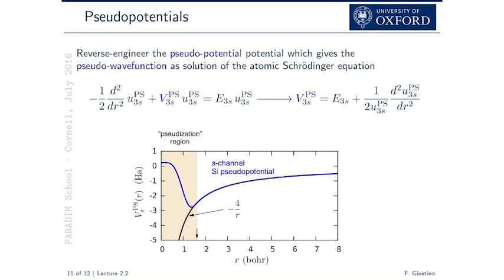So this operation actually is absolutely critical because, what you can try as an exercise if you want today, try to do any of the examples you did, okay, crank up, so you use maybe a cutoff of 25 Rydbergs, try to do the same calculation and put 500 Rydbergs there. You'll see how long you're going to wait. Okay? And to do those nodes, you will need something of that order, because that's basically atomic physics. Okay? So the use of pseudopotential is what really enables computational material science, studying many atoms. So that's really, really critical.